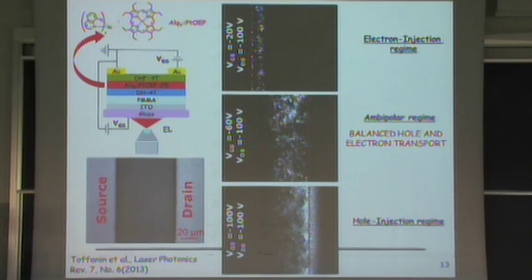So here is what I observe under the optical microscope. When I apply an ambipolar polarization, so under the ambipolar regime, the electrons and the holes are very balanced. So we obtain the light emission in the center of the channel, and it is very wide. It reaches almost the total length of the channel. An important thing is that there is no light emission under the electrode.